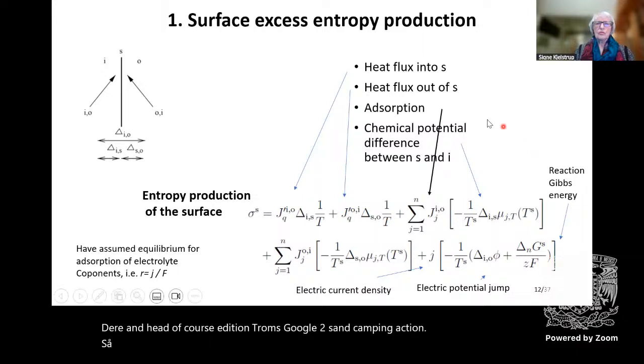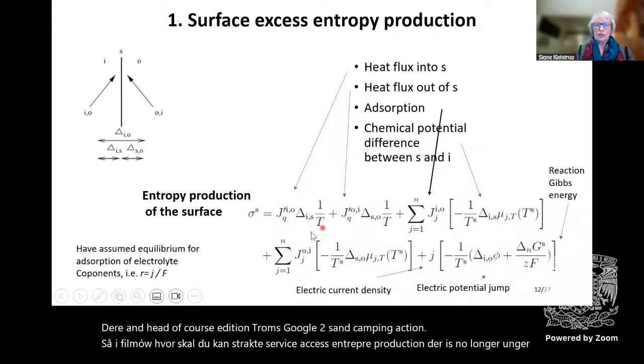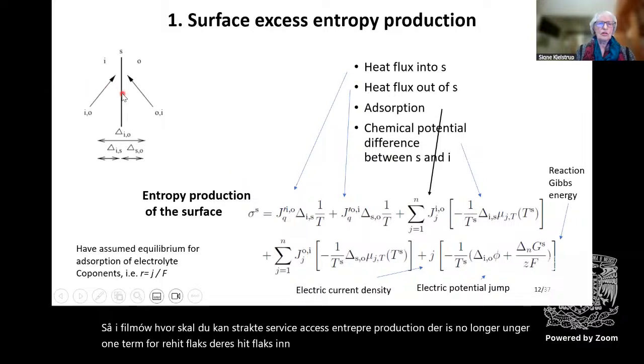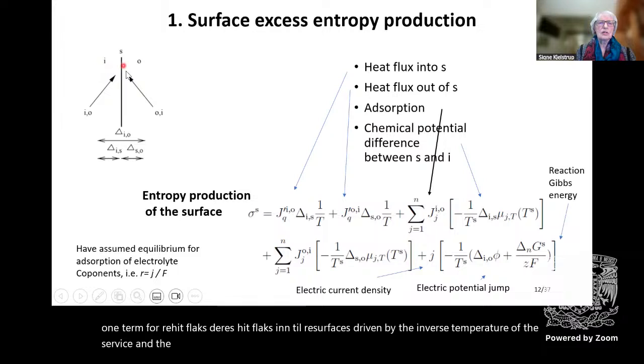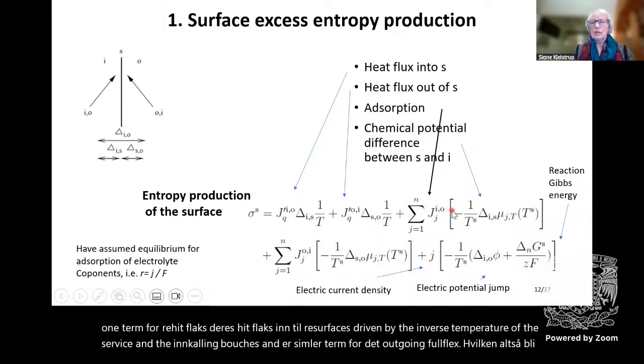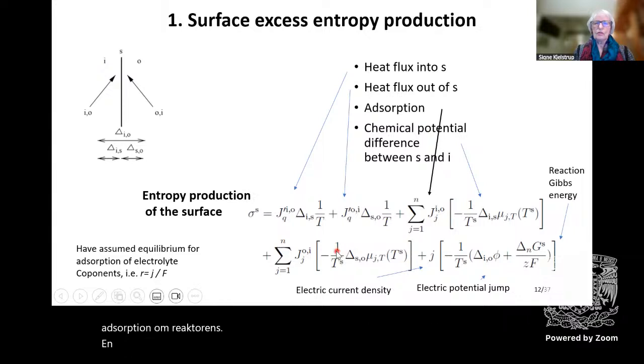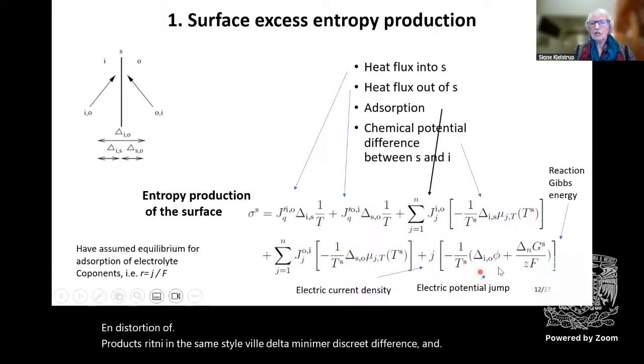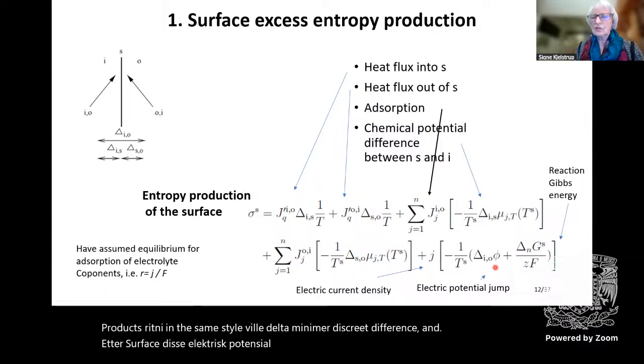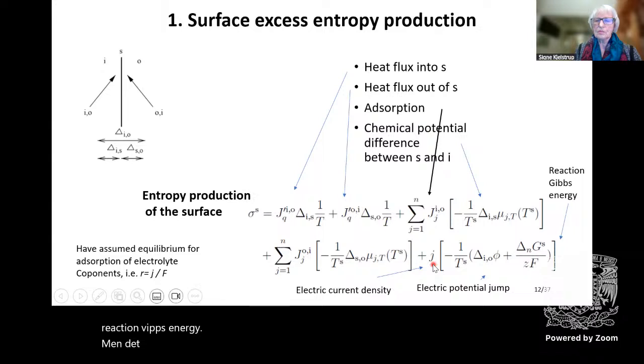So if I now was going to construct the surface excess entropy production, there is no longer only one term for the heat flux. There is the heat flux into the surface, driven by the inverse temperature of the surface and the incoming bulk phase, and a similar term for the outgoing heat flux. There can also be adsorption of reactants and desorption of products written in the same style with a delta, meaning a discrete difference. And at the surface, it is an electric potential jump that counts, and that is a scalar, and it connects with the reaction Gibbs energy when the electric current density is proportional to the reaction rate.